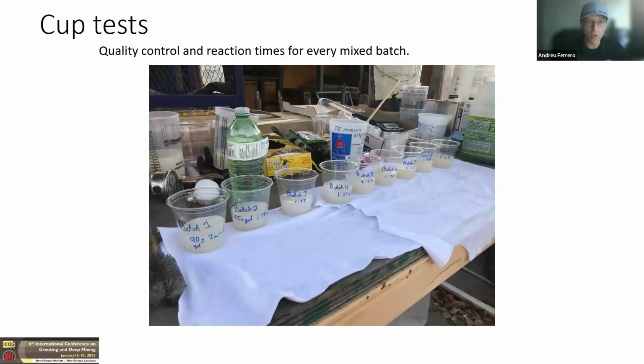These are quality control and reaction times for each batch that was mixed. This is the acrylate grout, and you can see there that the reaction times are generally right around 1 minute and 30 seconds to 2 minutes. And that is in a cup test.